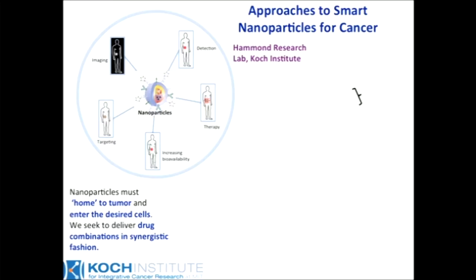So let's go over this briefly with a cartoon. We have a core which contains drug molecules, shown here as these yellow balls, and that nanoparticle can encapsulate it. We put down a hydrated layer for stealth, and then we introduce molecular ligands, represented by these small triangles here, which can bind tumor cells specifically and induce cell uptake. So this is the generic or general idea of a targeted nanoparticle. And the sizes of these nanoparticles can be compared to the sizes of, let's say, an antibody or a virus, somewhere in that range there.